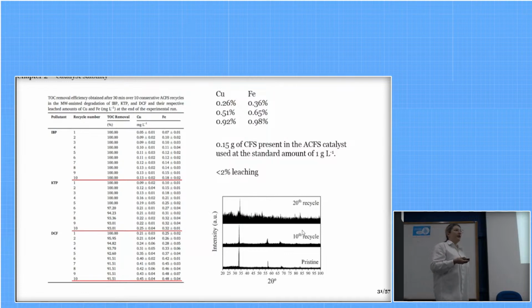As we knew that our catalyst was able to produce several recycles, we tested its structural stability by investigating the leaching of the metallic particles loaded into the material. So we used atomic absorption spectrometry to measure copper and iron content, which resulted in less than 2% leaching of these metallic particles from the catalyst, and we observed an increase in the amorphous phase for carbon, but without losing the crystallinity of the chalcopyrite particles in the 10th recycle, which corroborates the structural stability of this material.